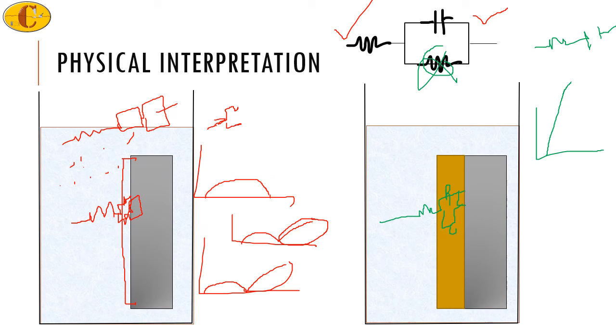As the coating starts degrading, it will start developing pores. When it starts developing pores, then you will have the arc formation. So arc formation indicates that now you have the resistance coming into play parallelly, and you can change the circuit used for fitting in the case. So it is not compulsory to keep using the same circuit for all the conditions in your study. If you see that physically there is a change in your system, you do definitely need to change the circuit and get the right parameters and fitting.